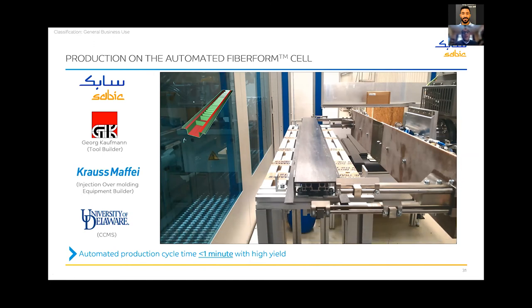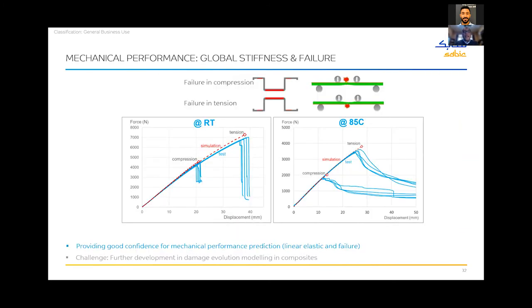Now, it's one thing to make a beam. You'll say, Nikhil, how good was this beam at the end? So we went to the University of Delaware, where we did testing both in compression and tension on this 1 meter long beam, both at room temperature and at elevated temperature. And we did this both under quasi-static testing conditions as well as drop impact conditions.